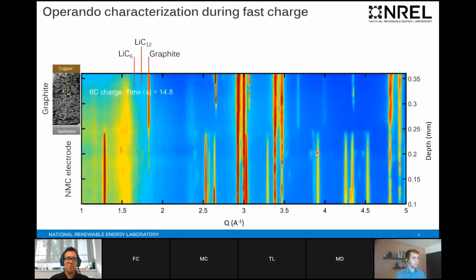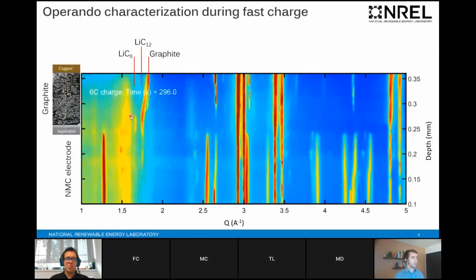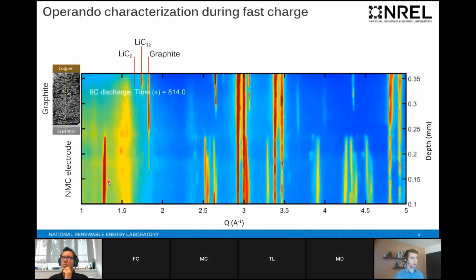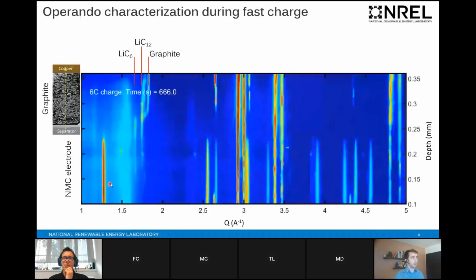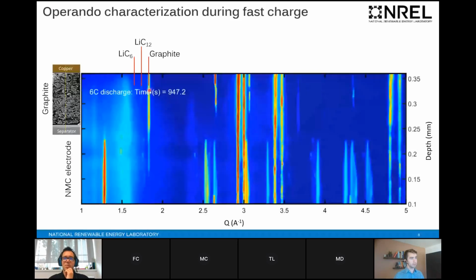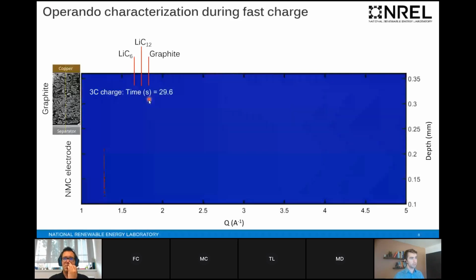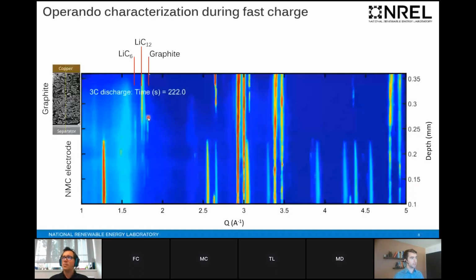And this is the raw data. So you can see this is the line profile. I should explain X-ray diffraction. We get peaks from certain crystallographic phases. Graphite, LiC12 or stage 2, and LiC6 have very distinct crystal diffraction peaks, and you can see them moving over and back as the electrode lithiates and delithiates here.